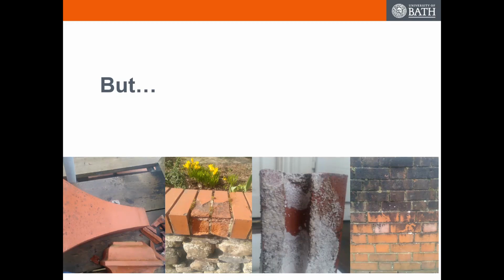That picture of bricks there, that's definitely freeze-thaw damage. That's classic garden wall damage. But the pattern of the damage, that very flat spalling, is where there's a slip plane. When the bricks have been extruded, there's a slip plane where that skin is dragging during extrusion. A few millimeters below is where you have this long streak of pores, and that's what's cracked as it's filled with water in the icy cold Cardiff winter. Well, soaking wet Cardiff winter.